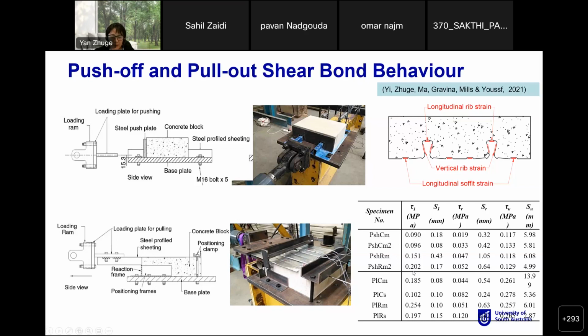And another thing is tau R, which is the other one. So that is the residual bond. And finally, tau U is the ultimate bond. And you can see for the CRC, we got very similar results to the normal concrete. So that is normal concrete for the push 1 and push 2. And that is for the push test for crumb rubber concrete, which is consistent.